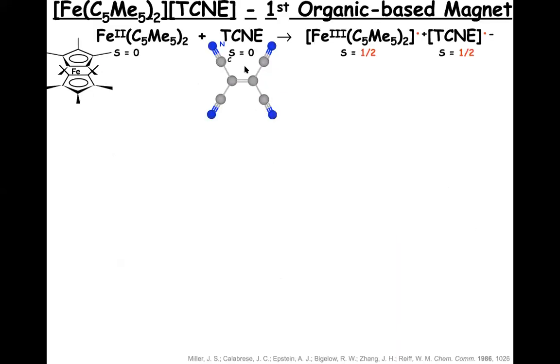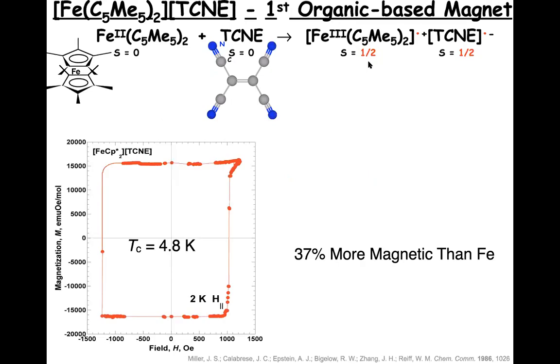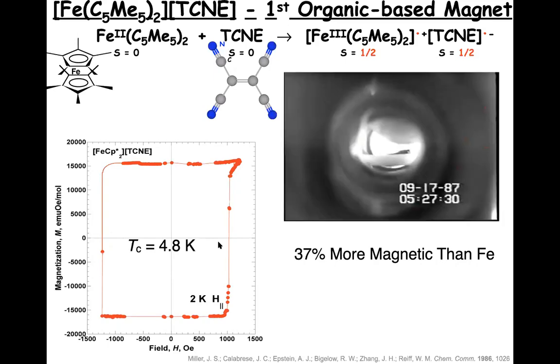And I'm just going to simply tell you, reacting decamethylferrocene with TCNE oxidizes the iron 2 to iron 3, spin 1/2. TCNE forms the radical anion, a very similar structure for it. And in fact, I'm simply going to tell you point blankly, it magnetically orders as a ferromagnet at 4.8 Kelvin. Here are hysteresis loops with a 1000 Gauss coercive field, which is half the width between these two features over here. And it is a bulk three-dimensional ferromagnet below 4.8 Kelvin.